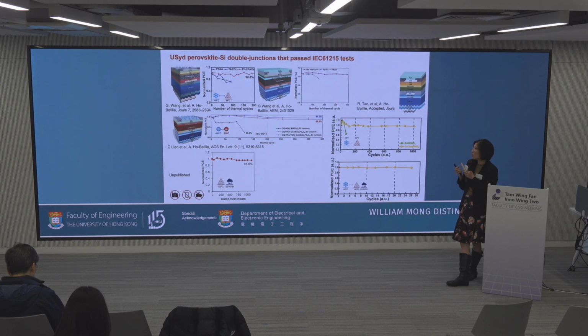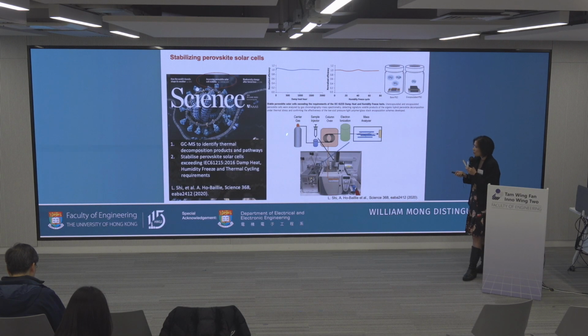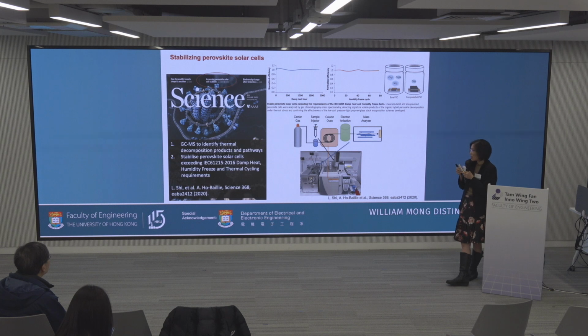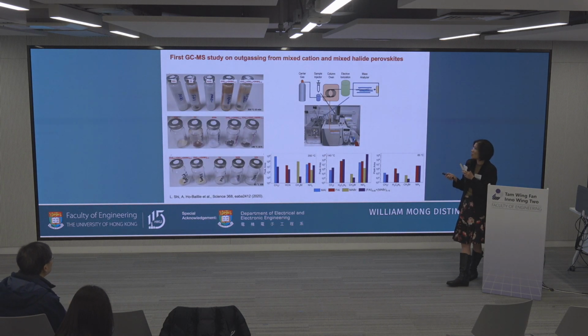So how do we manage to do that? We have years of experience learning about the degradation of perovskite in heat and moisture. We build on the work that we did in 2020, where we had the very first GCMS study of perovskite degradation. GCMS is known, people use GCMS for all sorts of stuff, but no one put the two together that you can use GCMS to study the degradation of perovskites. So why is GCMS good? Because GC allows you to separate the products, and it's really good for mixed cation and mixed halide perovskites.